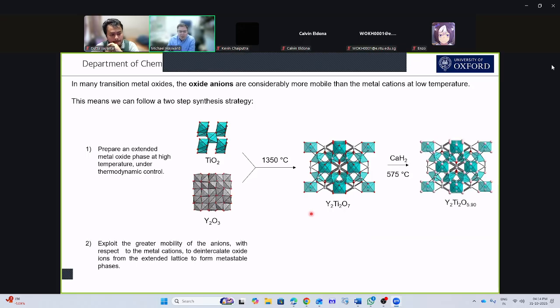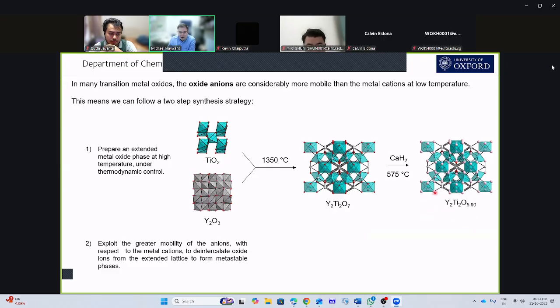What I can do now is treat these with a reagent, and I'll talk about these hydrides in just a second. And now I can exploit the higher mobility of the oxide ions in this framework than the metals to extract oxygen from the system and make a reduced compound, so Y2Ti2O5.9.